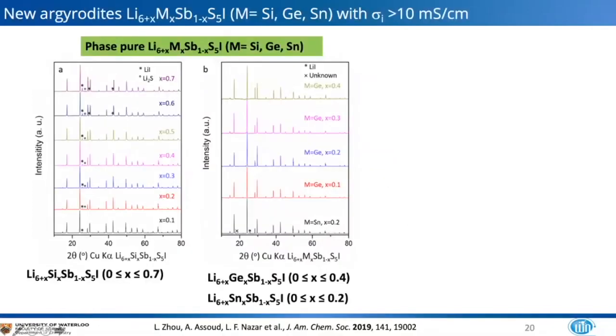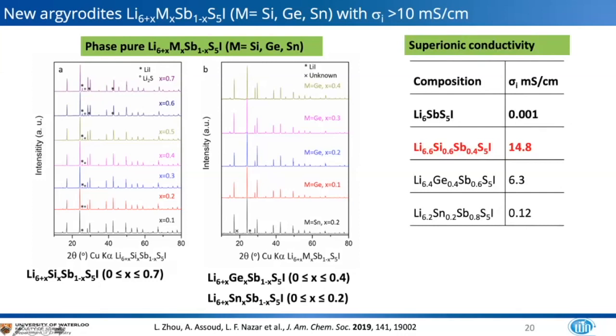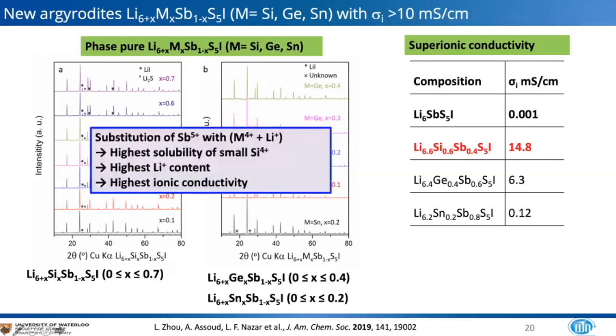So my grad student Lidong Zhou discovered that we could make highly conductive iodides using the antimonide version of this material, and these have conductivity upwards of 10 millisiemens per centimeter. This shows the diffraction patterns of the silicon, germanium, and tin analogs, and the superionic conductivity is shown here as high as almost 15 millisiemens for this particular composition. And so the point is that when we substitute antimony with the smallest aliovalent dopant, which is silicon, that gives rise to the highest lithium content, as you can see here, and that gives rise to the highest conductivity.